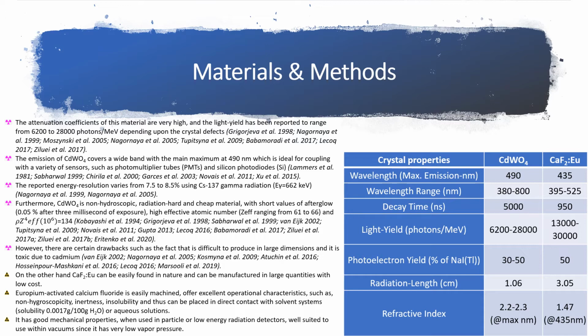On the other hand, europium-activated calcium fluoride can be easily found in nature and can be manufactured in large quantities at low cost. Europium-activated calcium fluoride is easily machined, offers excellent operational characteristics such as non-hygroscopicity, inertness, insolubility, and thus can be placed in direct contact with solvent systems or aqueous solutions. It has good mechanical properties when used in particle or low-energy radiation detectors, and it is well suited to use within vacuums since it has very low vapor pressure.